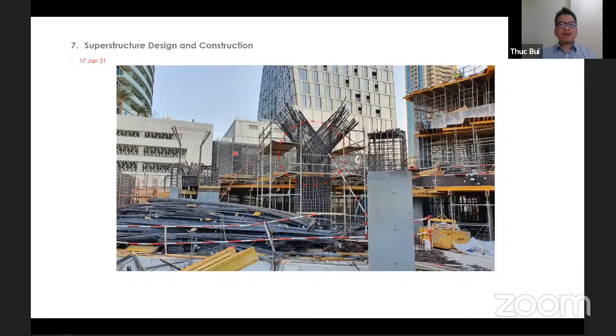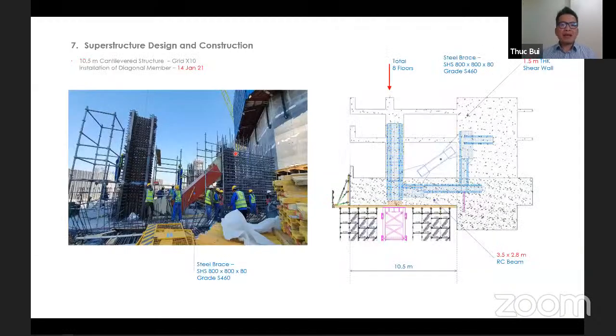This is a photo of the V-shaped column on site. Vertical rebars are being installed. And this is the construction of the 10.5 meter cantilever structure at level 3. As you know, it supports a planted column, and this planted column supports 8 floors above. To avoid locked-in stress in the steel diagonal brace due to vertical shortening of the shear wall and the column, we do full welding at one end of the brace, and the connection at the top end will be fully welded after completion of the level 15 floor slab. And then after that, we can remove the temporary prop underneath the beam.